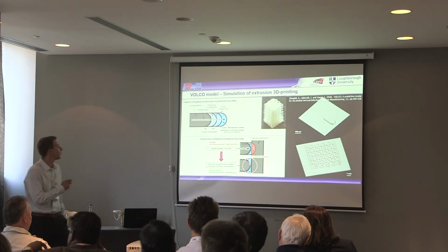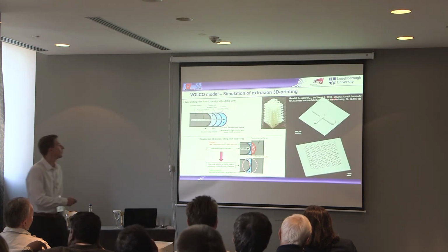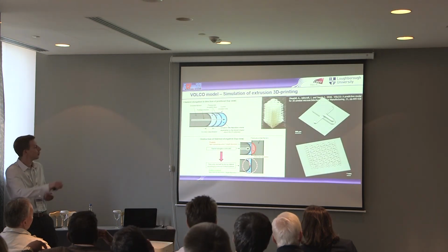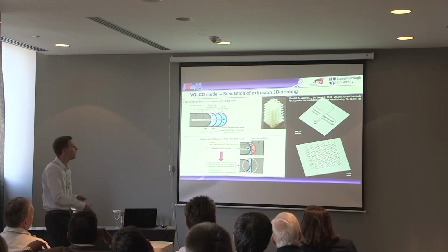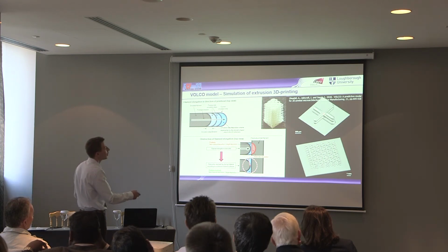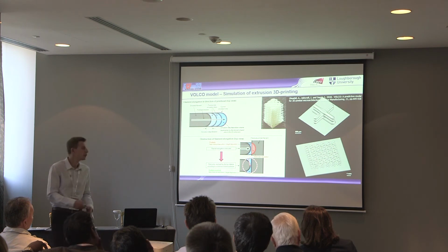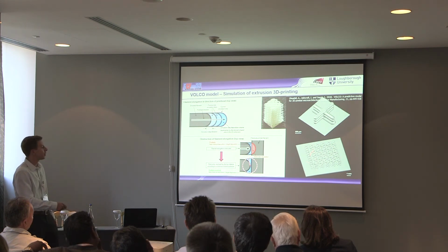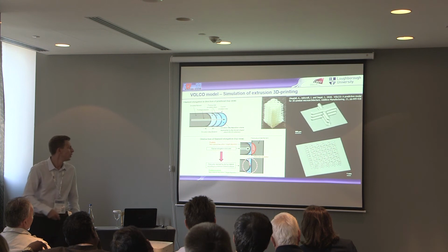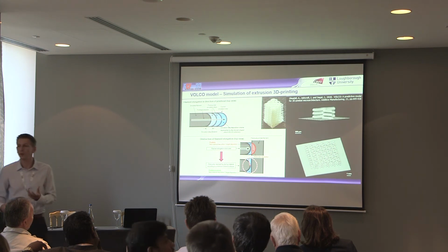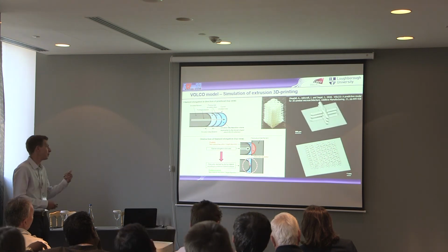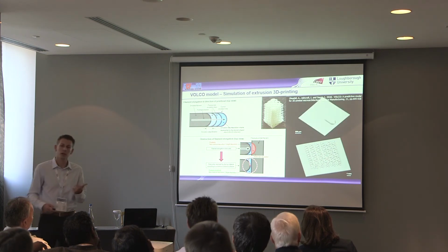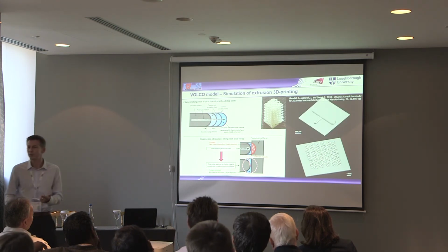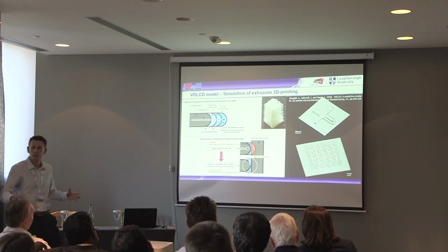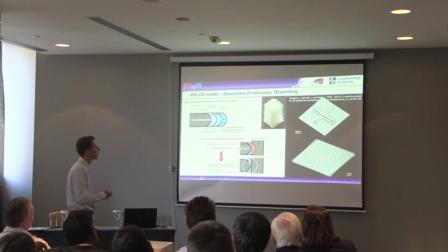And then the final little bit is simulating the extrusion process. So this is simulating a filament being deposited and then another filament going across it. And you can see as it's going across, it's slightly widening because it's being obstructed. And then this is a much larger scaffold structure, just showing that it's a really simple simulation process. It's basically just assuming material is coming out of the nozzle and material can't be deposited where there's already material, so it will have to spread out. That's the simple assumption of this.